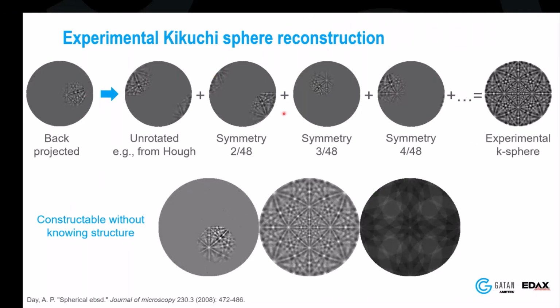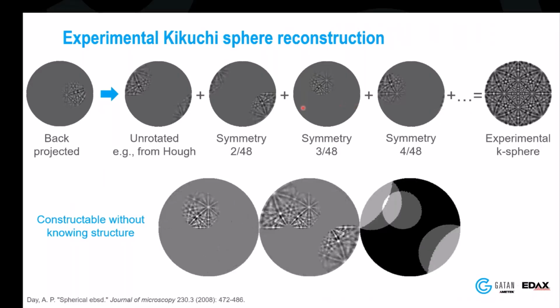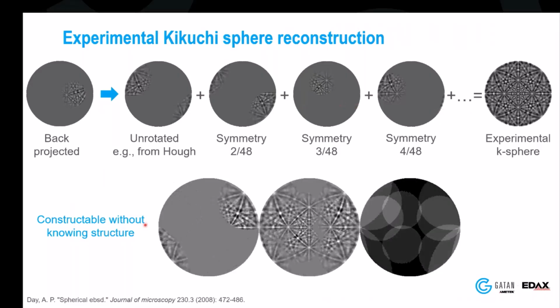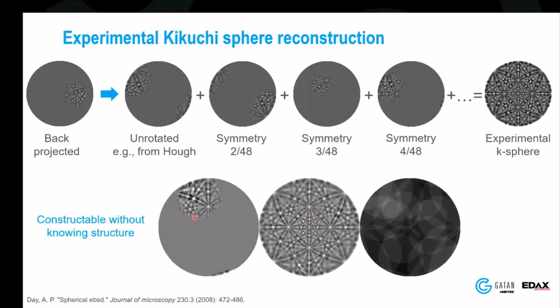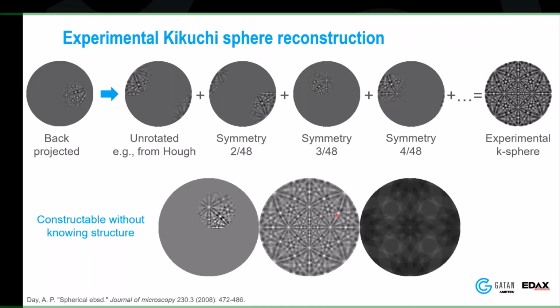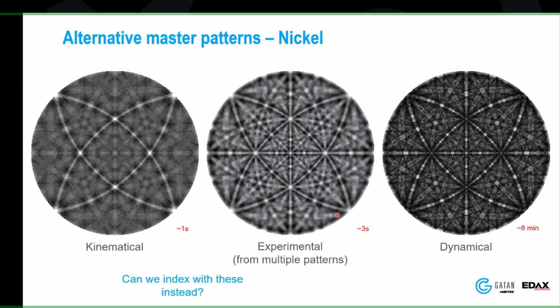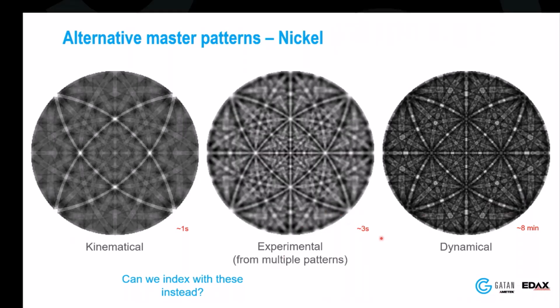So if I have enough high quality patterns in my material, and I know the base structure of my material, I can essentially reconstruct this by finding the orientations of the patterns that I have, and then build my master pattern from doing this. And this is the crazy part here. This right here is for nickel. You can see the dynamical simulation takes 8 minutes, while the experimental takes around 3 seconds.